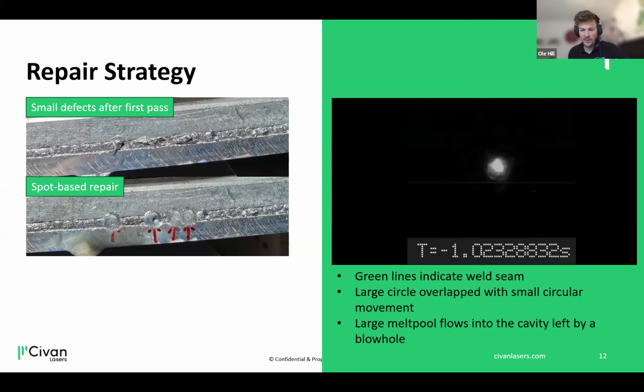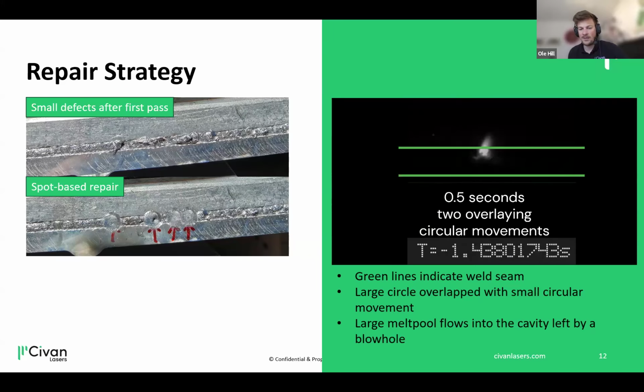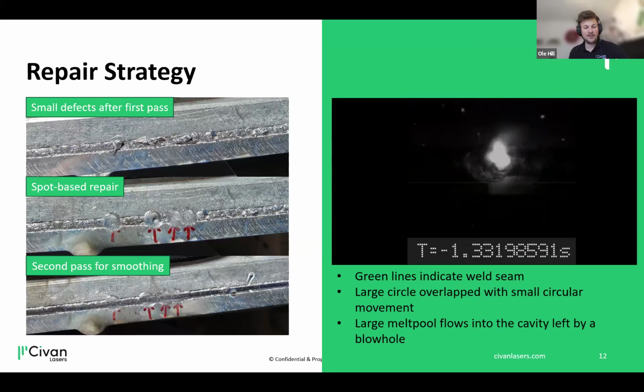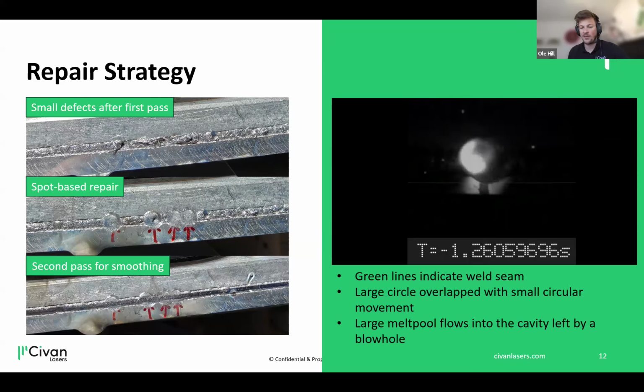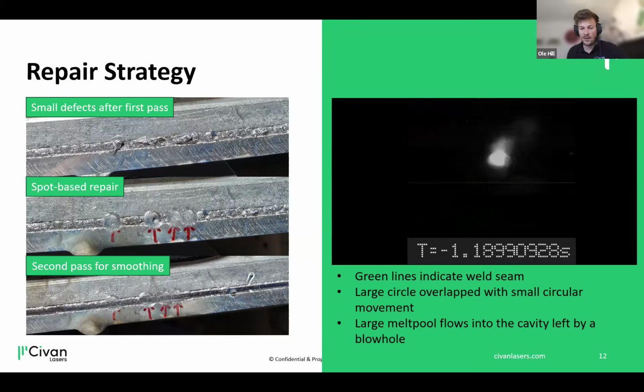And this process in the video looks quite long, but it is just over 0.5 seconds. So even if you get a few blowholes in one weld seam, it is a very fast repair. And as I mentioned previously, we then do a second pass over the weld seam anyways, which also smoothens out the repair. So it can be done in a way where it's not visible afterwards.